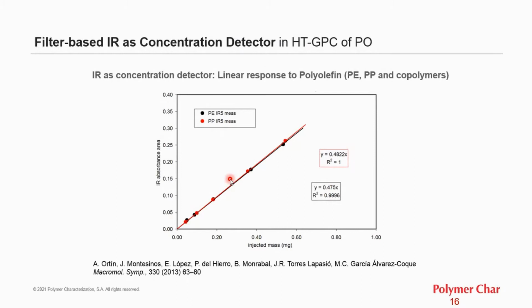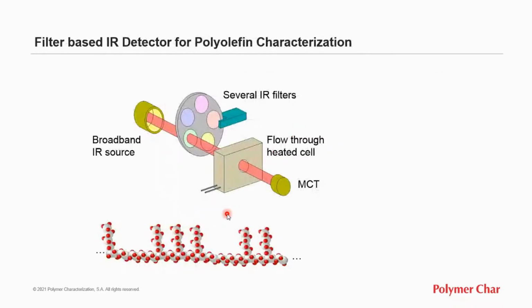Another big development in separation techniques for polyolefins has been the application of infrared as detector, especially in the case of GPC analysis of polyolefins, instead of the refractive index detector. We proved that the IR detector shows a linear response to polyolefins, with the same sensitivity to polyethylene or polypropylene or copolymers, as we see in this graph. Some words on how that works.